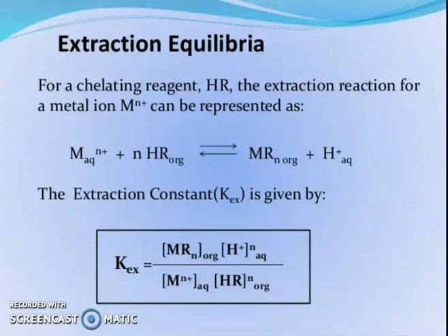Extraction equilibrium. For chelating reagent HR, the extraction reaction for metal ion Mn+ can be represented as Mn+ plus nHR organic, in equilibrium with MRn organic plus nH+.